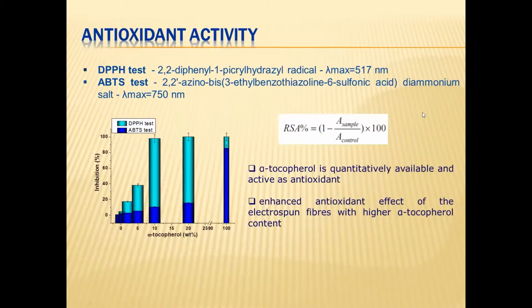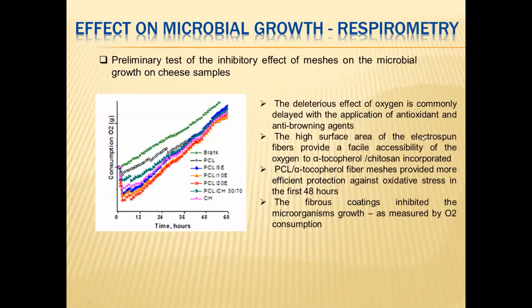The antioxidant activity of the coatings was tested also by DPPH and ABTS tests, and the radical scavenging activity was calculated, measuring the inhibition of the free radicals. The results obtained showed an enhanced antioxidant effect of the electrospun fibers with a higher alpha-tocopherol content. The effect on microbial growth of the fibrous coatings obtained was tested by respirometry. A preliminary test was performed of the inhibitory effect of meshes on the microbial growth on cheese samples.